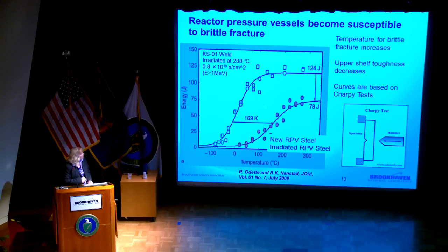These curves are based on what's known as the Charpy test. They take a coupon of material. This sample is a coupon, about 10 millimeters by 50 millimeters. They just hit it with a hammer. It already has a notch in it. They measure how much energy it takes to fracture, and they do that over and over again, and then they draw the curve. There are already samples of this type that have been looked at, irradiated and measured to draw these curves.